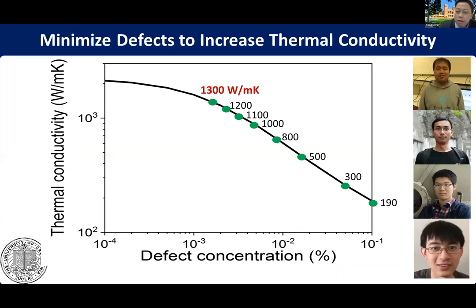So my students have carefully controlled the synthesis conditions, including temperature, flow rates, substrates, precursors, and so on. So we're able to make gradual improvement of the thermal conductivity values from initially 190 to 300, 500, 1000, 1100, 1200, and eventually 1300 watt per meter Kelvin. We also made careful verifications over 100 samples and get consistent results.